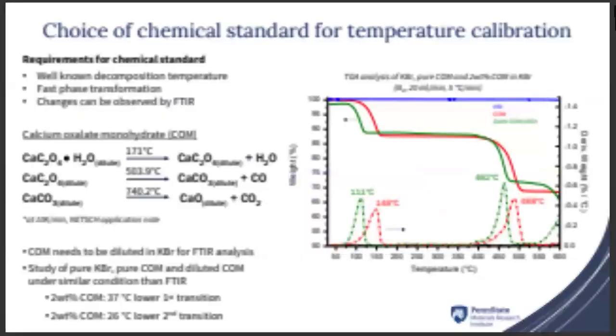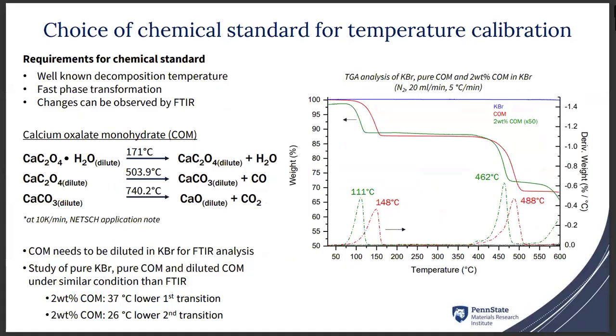In order to study that, we decided to use a commonly used standard for thermogravimetric analysis. The choice of this standard is because it has a well-known decomposition temperature, a fast phase transformation, and the change can be observed using FTIR. The compound we decided to use is calcium oxalate monohydrate, which leads to dehydration at around 171 degrees Celsius, then decomposition to form calcium carbonate at 500 degrees Celsius, and complete decomposition at 740 degrees Celsius. The first two events are of interest for analysis because they span within the temperature range our cell is capable of.